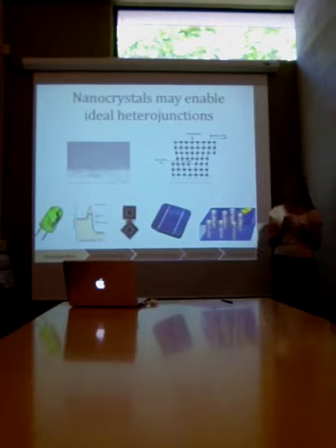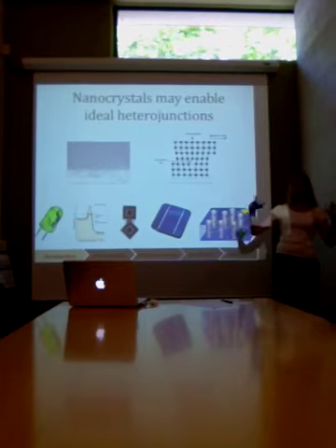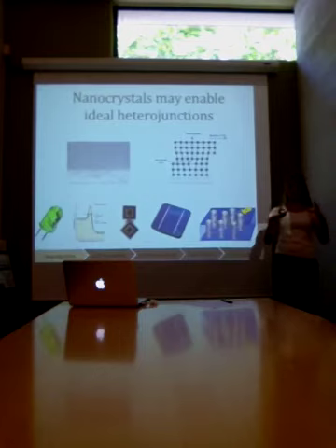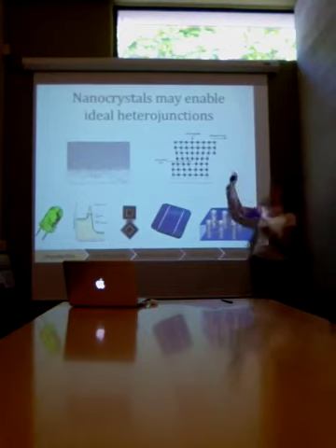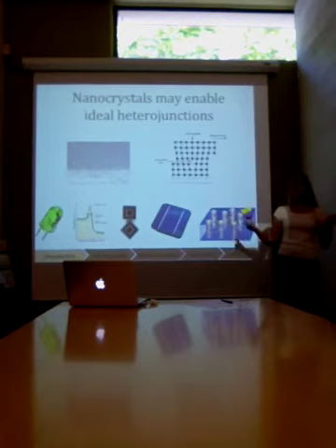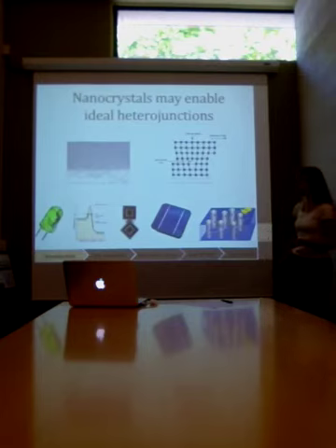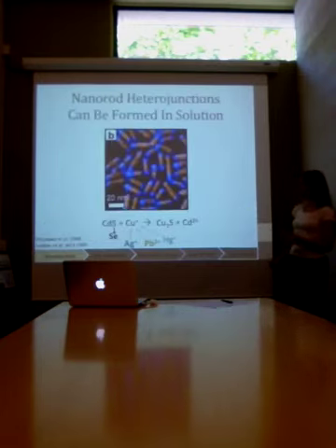So let's imagine we take two materials that have fairly low lattice mismatch, and now let's shrink their interfacial area, let's shrink the heterojunction, to be smaller than the characteristic distance over which we have a misfit dislocation. If we could do this, we would have effectively a perfect heterojunction with no defects at the interface. And in nanocrystals, it is possible to do this.